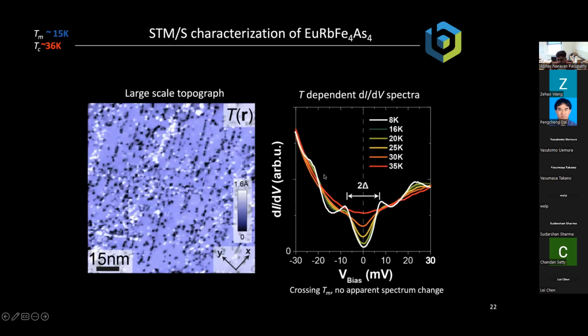Now, what we can do with the STM is we can measure the local density of states. So this is STM spectroscopy. So we measure the differential conductance as a function of bias that we apply between the tip and the sample. And we can see very clearly as we go below the superconducting transition temperature, this is 35 Kelvin, you start to see a little gap appear in the spectrum. That's a signature of superconductivity. And as you go down to low temperature, this is 8 Kelvin, you can see this gap develop into a nice superconducting gap, as many superconductors have.